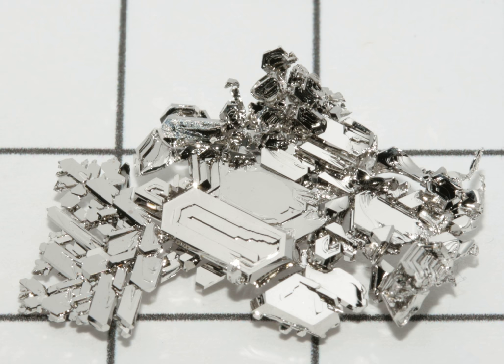Pure platinum is a lustrous, ductile, and malleable, silver-white metal. Platinum is more ductile than gold, silver or copper, thus being the most ductile of pure metals, but it is less malleable than gold. The metal has excellent resistance to corrosion, is stable at high temperatures and has stable electrical properties. Platinum does oxidize, forming PtO2, at 500 degrees Celsius. This oxide can be easily removed thermally. It reacts vigorously with fluorine at 500 degrees Celsius (932 degrees Fahrenheit) to form platinum tetrafluoride.